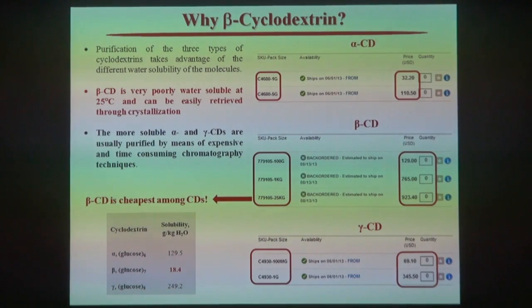So here you can see beta CD actually has very poor water solubility at room temperature, so it can be easily retrieved through crystallization. However, in contrast, alpha and gamma CD are readily dissolved in water. So in terms of purification, to get purified alpha and gamma CD is not easy. That increases the cost. It is time consuming, and you also need chromatography techniques to purify alpha and gamma CD. So these two CDs are more expensive than beta. So we go for beta CD and do the reaction.